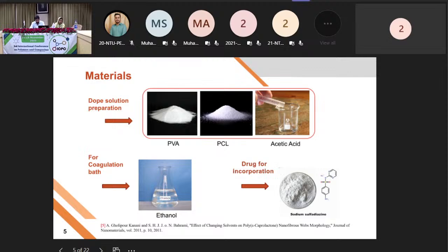In acetic acid, we developed a clear solution, and after developing the clear solution through agitation and heating, we add that solution to the dope tank of the extrusion machine. The extrusion machine used in this project is a wet extrusion process, and that solution was kept overnight for degassing purposes. Later on, it is extruded through the spinneret of the wet extrusion machine into a coagulation bath. That coagulation bath was formed of ethanol. The material becomes solidified in a fibrous form, and later it is stored after rinsing processes.